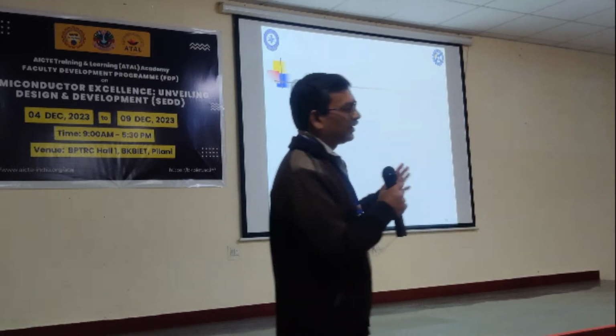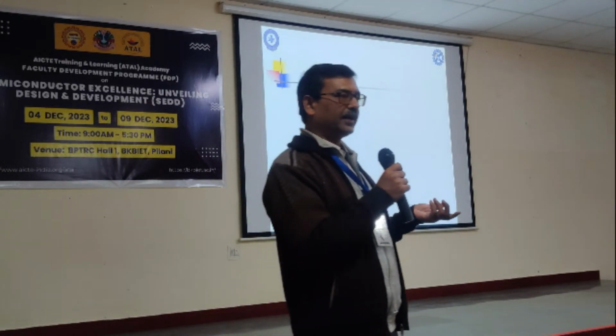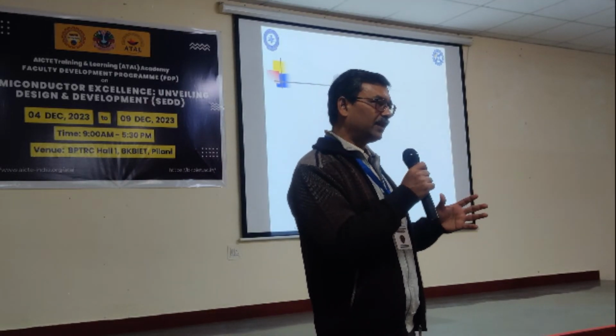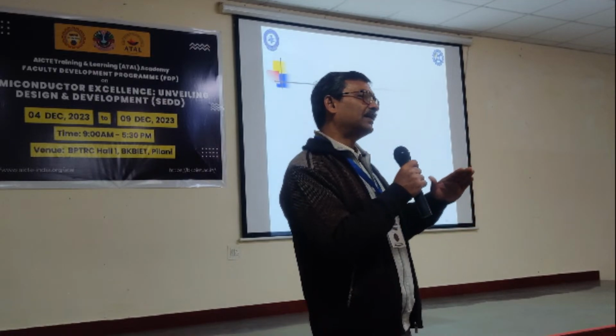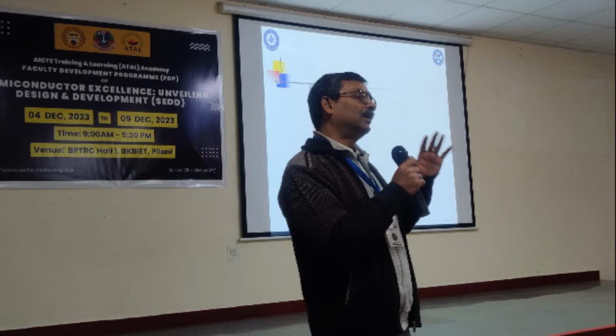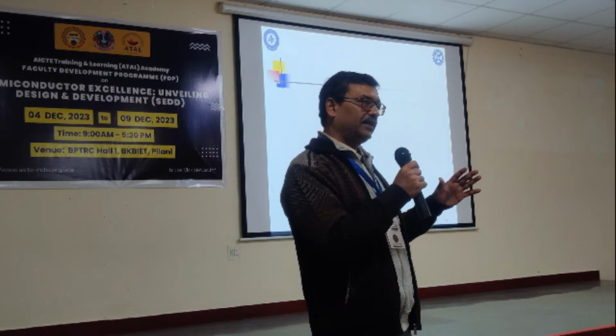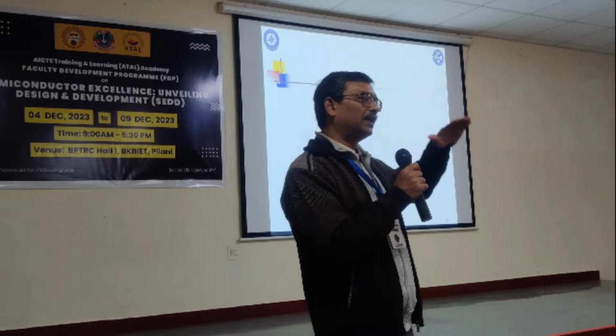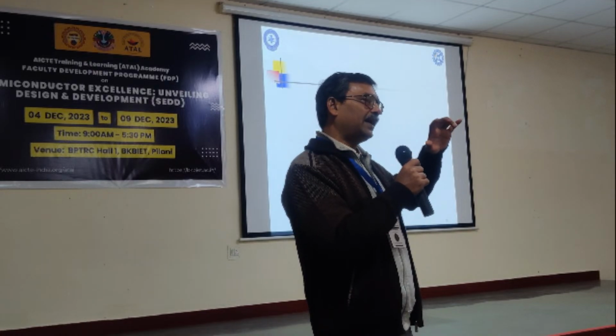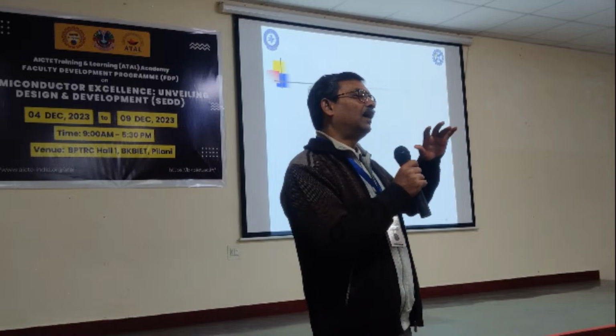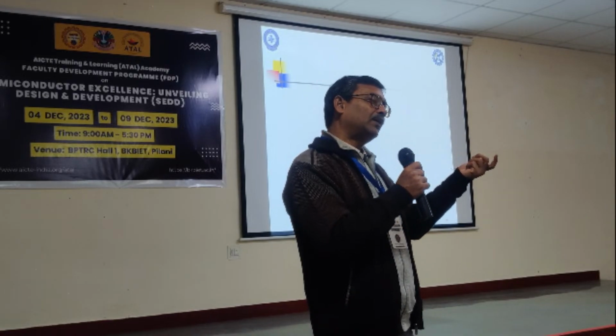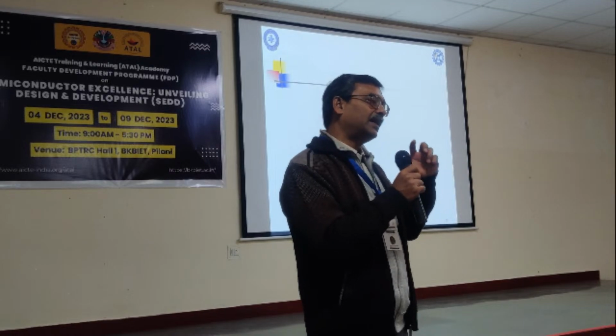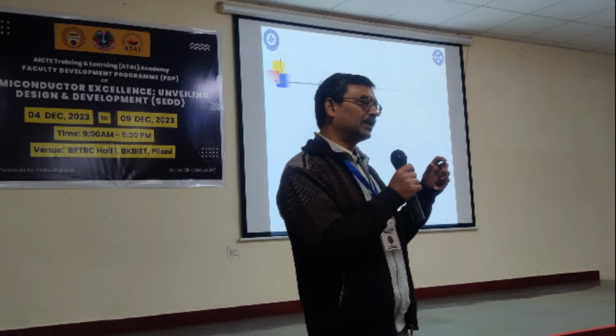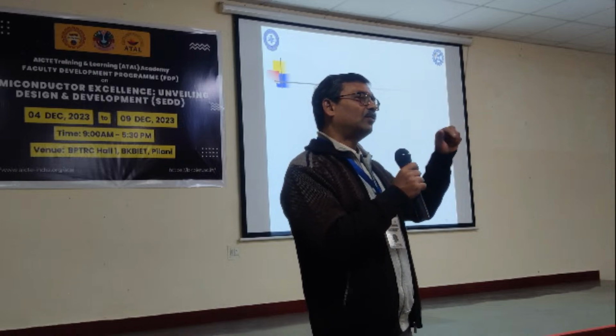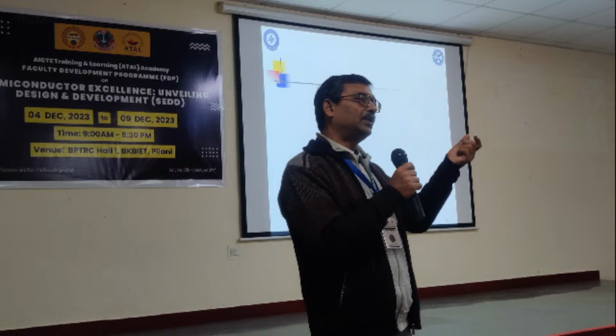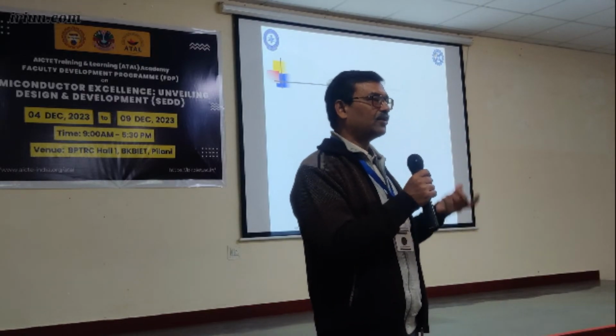As the lattice constants of sapphire and gallium nitride are very different, we need a buffer material, which acts to minimize the defect density creation. So if we grow a buffer layer with a certain thickness, then on top of that, whatever we grow will be the epi layer. Because after a certain thickness of gallium nitride formation, the lattice constant will be that of gallium nitride, and we are growing gallium nitride material on top of that. So that's why the buffer is required.